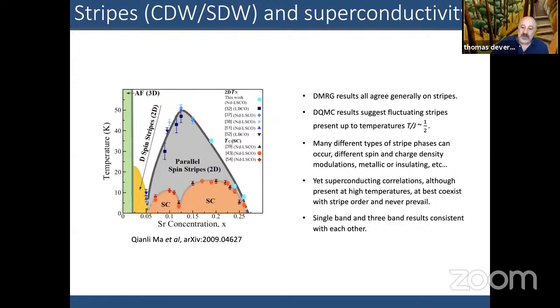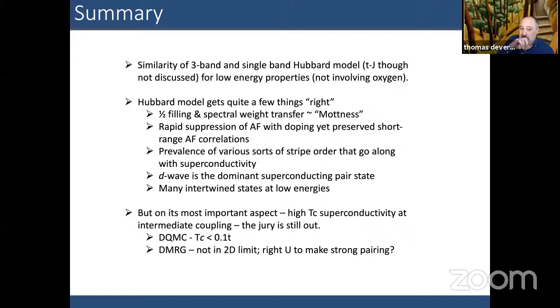Yet I think we're seeing that the superconducting correlations are there, and they have long range or quasi long range order, at least when T prime is turned on, but at best they coexist with stripe order, and they never seem to prevail all by themselves. So the single band and three band results seem to give results which are consistent with each other in these above mentioned four points. So the summary for this particular part: the three band and single band Hubbard models seem to show the same low energy properties.